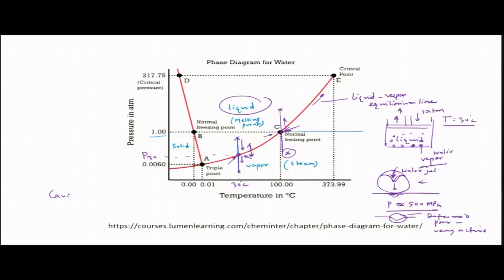Now the next stage, again another bubble forms because of the lowering of pressure. And in the second cycle, if pressure increases, that bubble will collapse again. So like that, repeated bubble formation and collapse lead to deformation of that particular surface and lead to extra corrosion of that deformed zone. So that way this particular degradation happens. Now this bubble formation and bubble collapse, and that collateral damage to the material, is basically termed as cavitation. Cavitation erosion, okay, or cavitation corrosion.